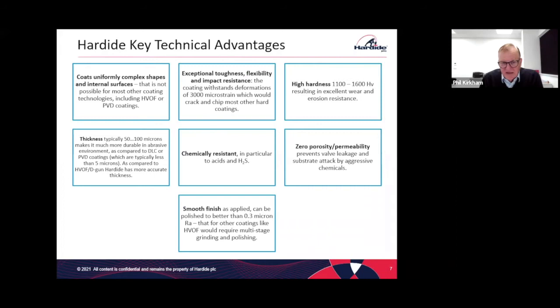Another big advantage is that it's very smooth as applied because of the way it grows. It follows the profile of the substrate material very, very accurately. So just a very light polish with silicon carbide prep or something like that is sufficient to give a very good surface finish. Again, compared to other coatings, they require generally grinding or machining to bring them back to a good surface finish because they're quite rough as they're applied. And with Hardide, you don't get that. You get a very smooth, conformal coating.